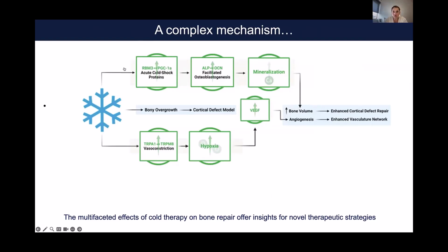So first, if we check on the bone volume, what we saw is that upon cold exposure, but very acute, only 15 minutes exposure to cold, we saw an upregulation, an increase in the detection of those acute cold shock proteins. And those acute cold shock proteins here are responsible for the upregulation of the osteoblast differentiation. And we did see as well an increase in ALP, the early marker of differentiation, but as well an increase of osteocalcin, which actually indicates the presence of a mature osteoblast capable of mineralization. So that was the first thing.